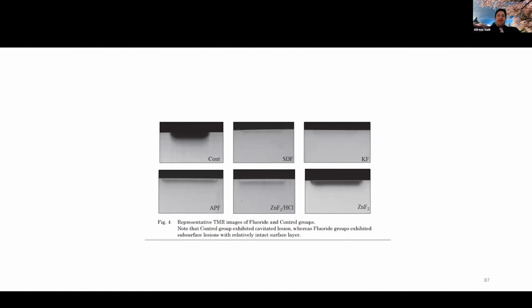So we did an effort. The main disadvantage of silver diamine fluoride, or at least one of the disadvantages, is the discoloration. That I'll talk a little bit about a way to tackle it. Many of you may know about that. But we did try to look at different ions instead of silver. So look at zinc, and that is what, again, GC is looking at. Instead of silver, because the metallic silver is what causes the discoloration. So if we come up with a formulation that has a non-discoloring metallic ion such as zinc with antibacterial properties, can we get the same effect as silver diamine fluoride?